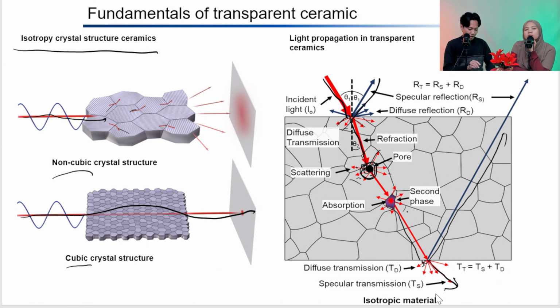So the point here is that pores should be minimized, maybe 99.9% density is preferred. Wow, it's very difficult to achieve. Yeah, to sinter and fabricate transparent ceramic. And we should also have very high purity of the material, so impurities or second phases should be avoided. Understood. What is more interesting is that here you talk about cubic and non-cubic, so it's about the properties, isotropy and non-isotropy, right? Yeah. If they are non-isotropic, they can generate different properties in different directions, so we should avoid that.